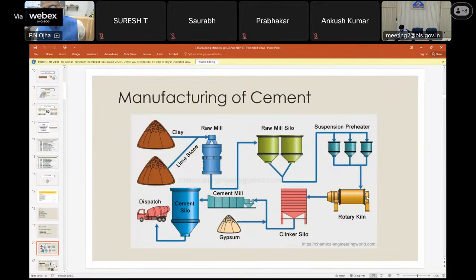And when out of this kiln, a nodular type of material comes, which is called clinker, and it is stored in the clinker silo. Then for grinding further, it goes to the cement mill, and then gypsum is added, and the material coming out is OPC. Here, if in the cement mill fly ash is added, then it becomes PPC, slag, then PSC, like that. Okay, so this is the flow chart of the manufacturing process of cement.